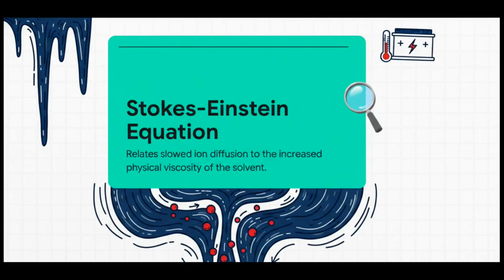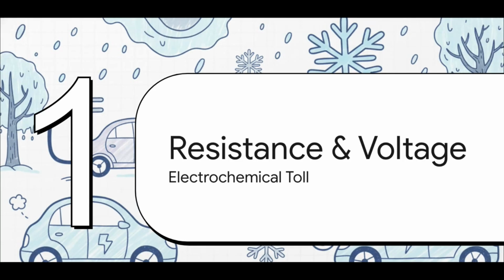The real villain here is perfectly described by the Stokes-Einstein Equation. While the ions are technically free, they are physically trapped. As temperatures plunge, the liquid electrolyte essentially transforms into molasses. The physical viscosity of the solvent increases drastically, which heavily limits the self-diffusion of the solvent molecules. So the lithium ions are perfectly ready to move, but they're trying to swim through a rapidly thickening fluid. The ionic conductivity crashes, not because the ions are paired up, but because they are physically bottlenecked by this cold, highly viscous solvent.